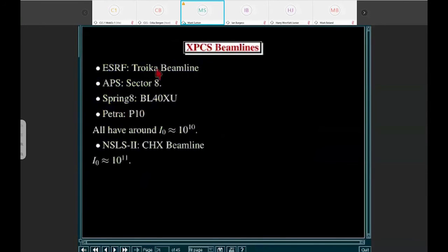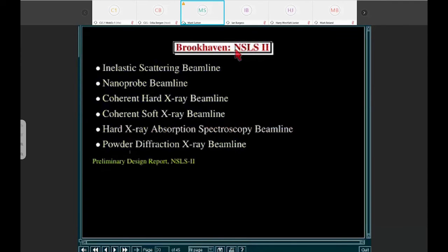Presently, there are several sets of beamlines, even a new one at the Sirius beamline as talked about by the previous speaker. There's a beamline at ESRF. The one I've been involved highly in is Sector 8 at APS. There's one at SPring-8, and Petra has the new DESY beamline in Hamburg, Germany. They all have a coherent intensity that we use. It's typically about 10 to the 10 photons per second in our mostly coherent beams. The ultimate third generation synchrotron was built at NSLS-II. It has a factor of 10 more coherence, and so you get about 10 to the 11. But of course, the future is the new multi-bend achromats.